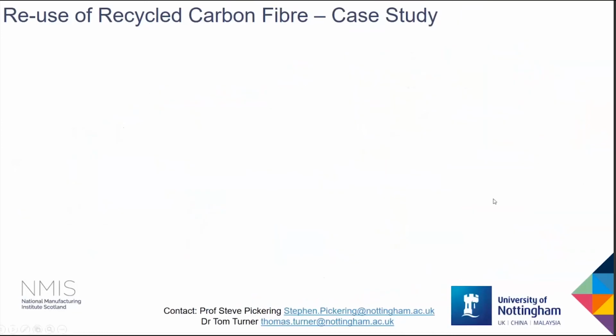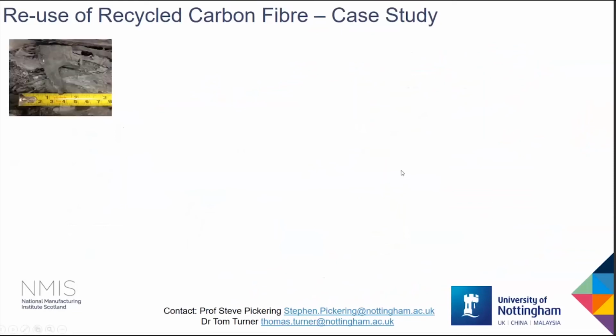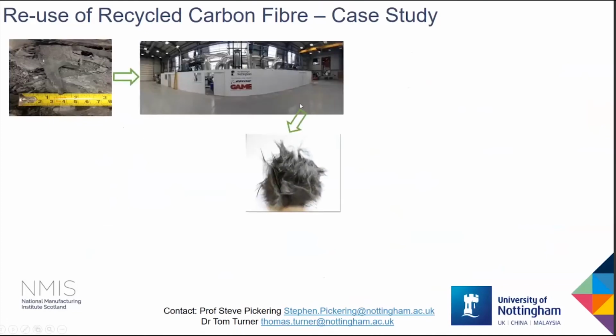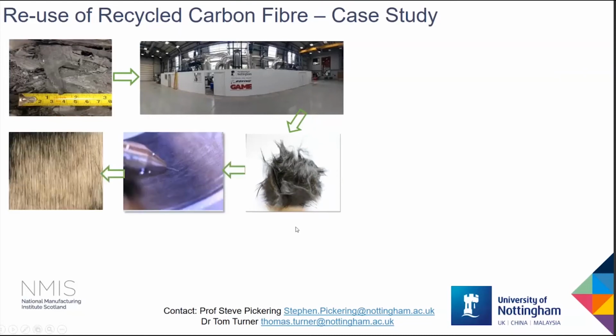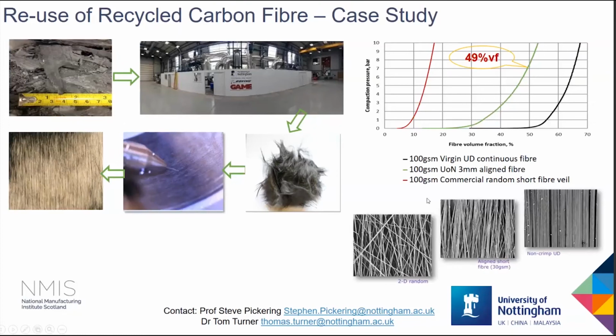This project has been done by the University of Nottingham and fully funded by Boeing. In the first stage, the researchers collected the end-of-life waste and did the first size reduction to make sure the pieces could fit into the pilot scale fluidized bed recycling process. At the end of this process, you can collect very clean and fluffy recycled carbon fiber. And a hydrodynamic alignment process has been developed to convert this fluffy fiber to highly aligned tape. A dry mat compaction test has been done to make sure we understand what kind of volume fractions you can achieve at different molding pressures.